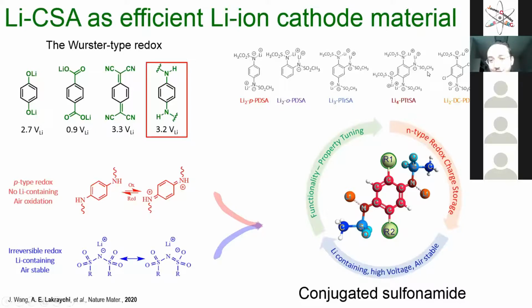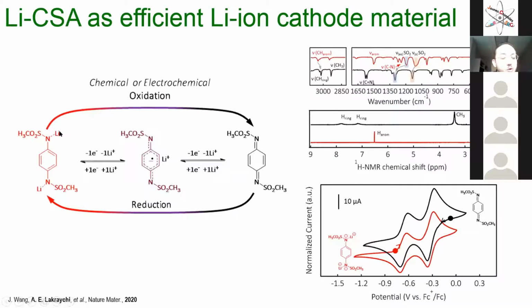And above is the first generation of molecules belonging to this class of material. Here I'm showing you the reference molecule. We call it lithium PDSA. On the left, you have the one that we synthesized. It is lithium containing and air stable. You remove one lithium, and then you form this intermediate molecule, which is a radical anion species. Then if you remove the second lithium, you end up with this neutral, fully oxidized molecule. So we were able to synthesize both the lithium containing and the fully oxidized.